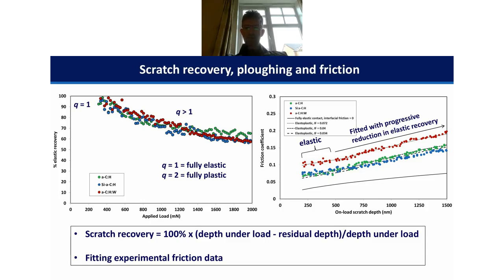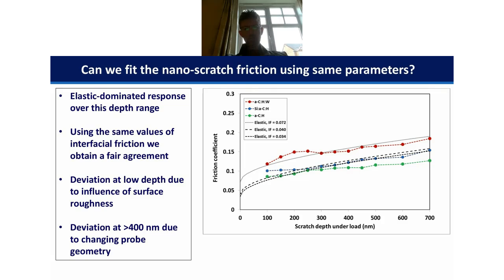So therefore, when we come to fit the frictional data as a function of depth, we can actually accurately fit this transition where we're seeing this gradual increase and then this quick, more rapid increase, this sort of bilinear behavior here. And we actually fit that with this equation here, which works quite nicely because we have this depth-dependent information here. We can also use those same parameters to fit the nanoscale scratch test, and this is a reasonably encouraging fit with exactly the same parameters.